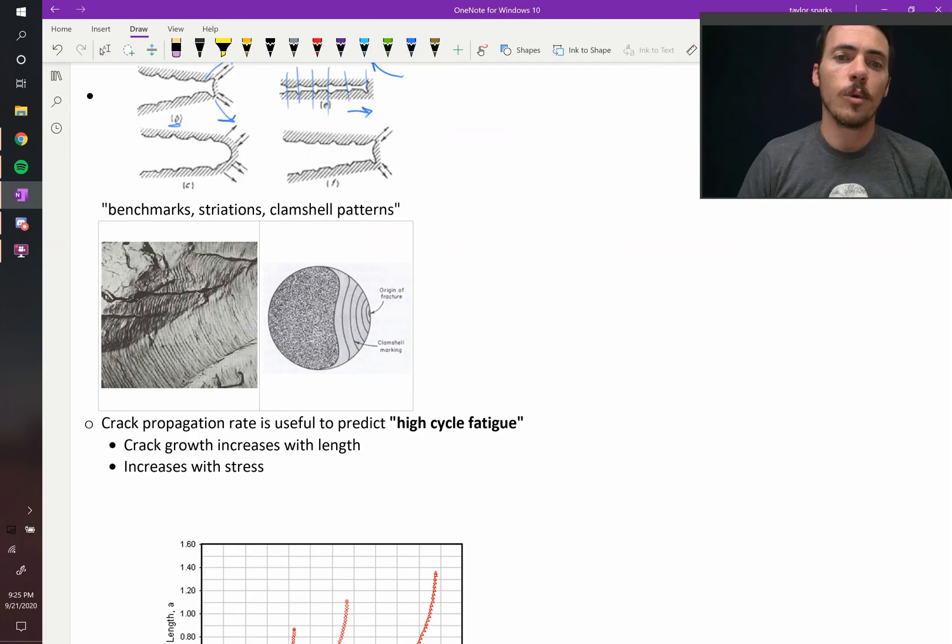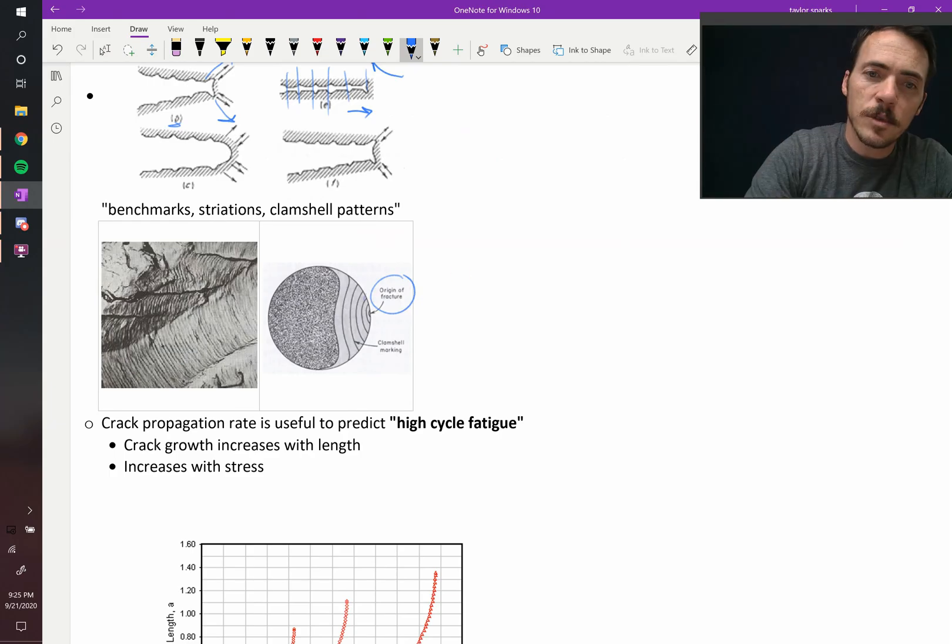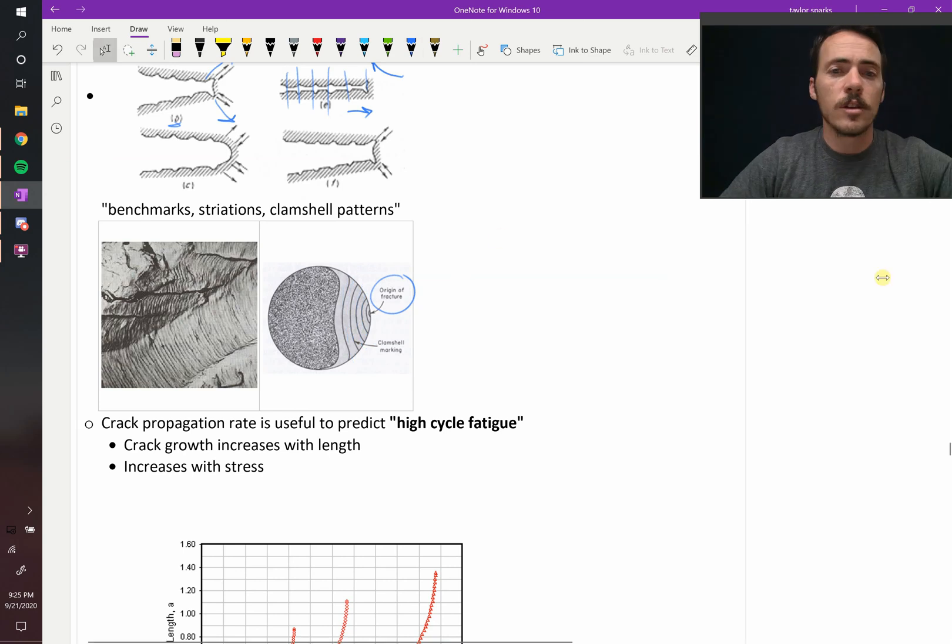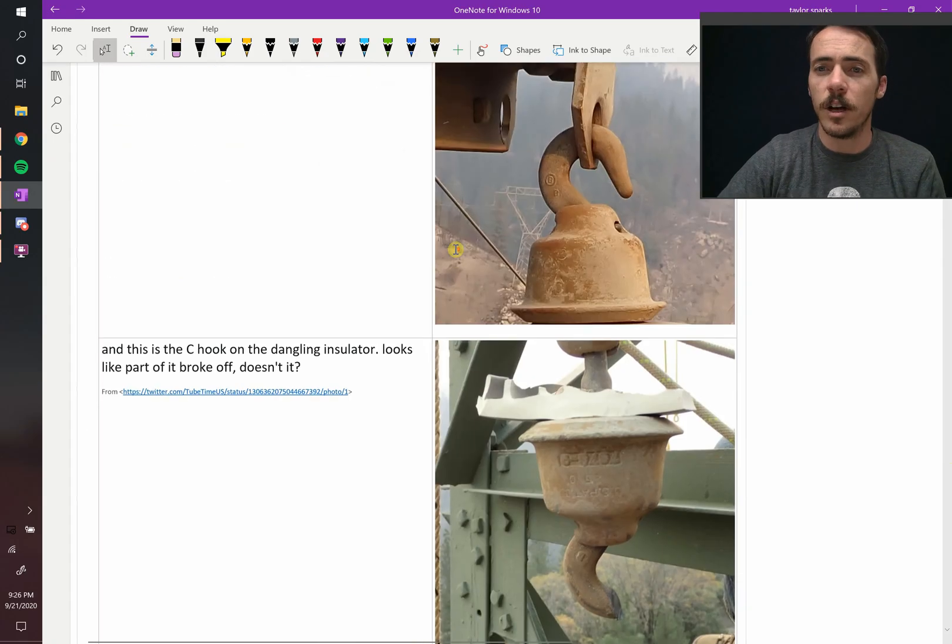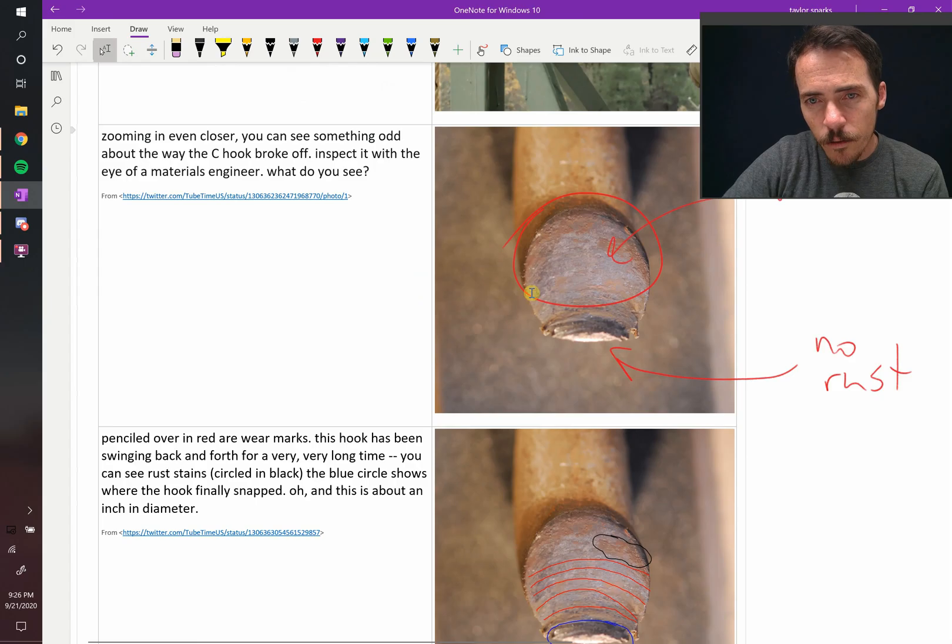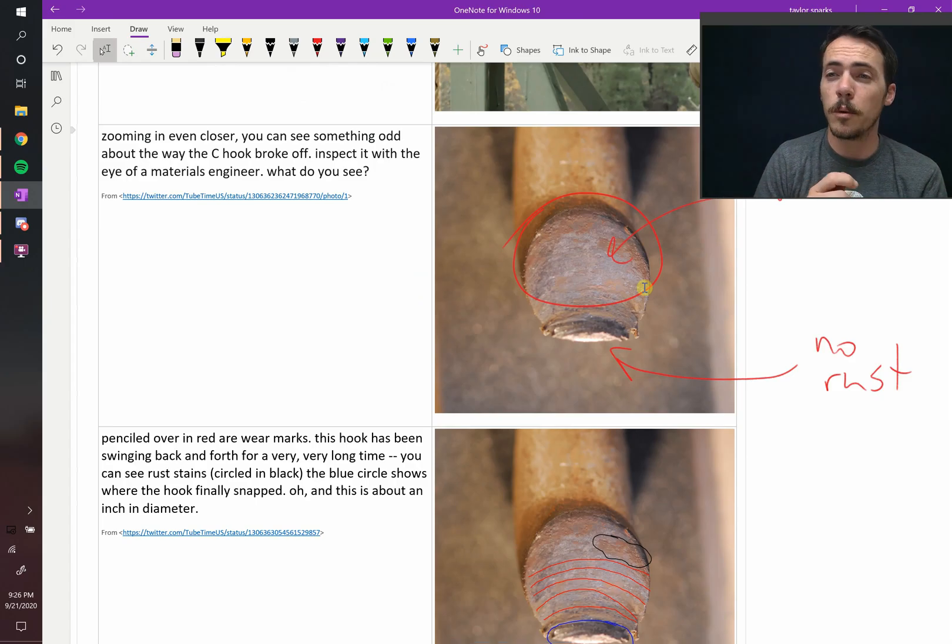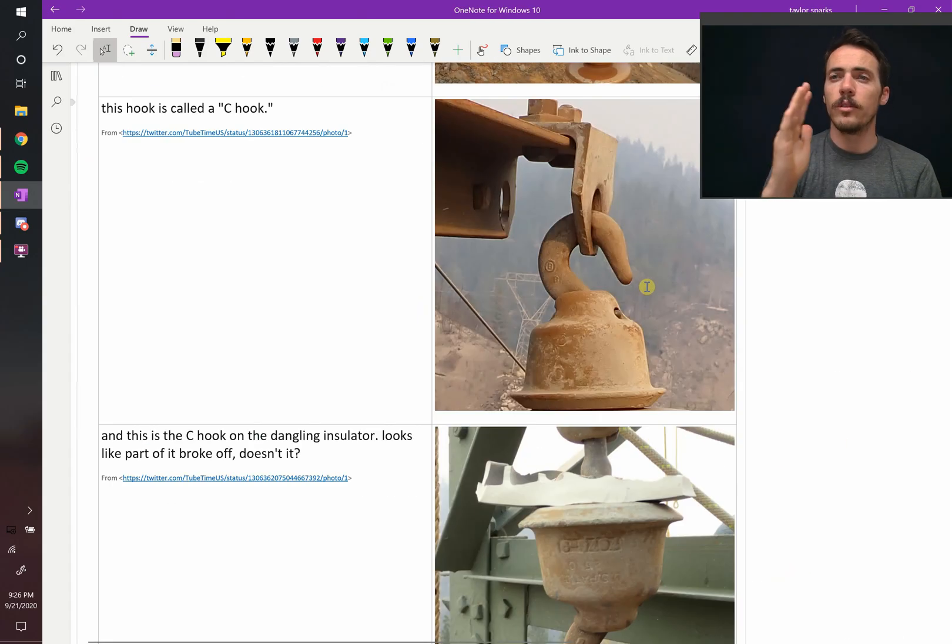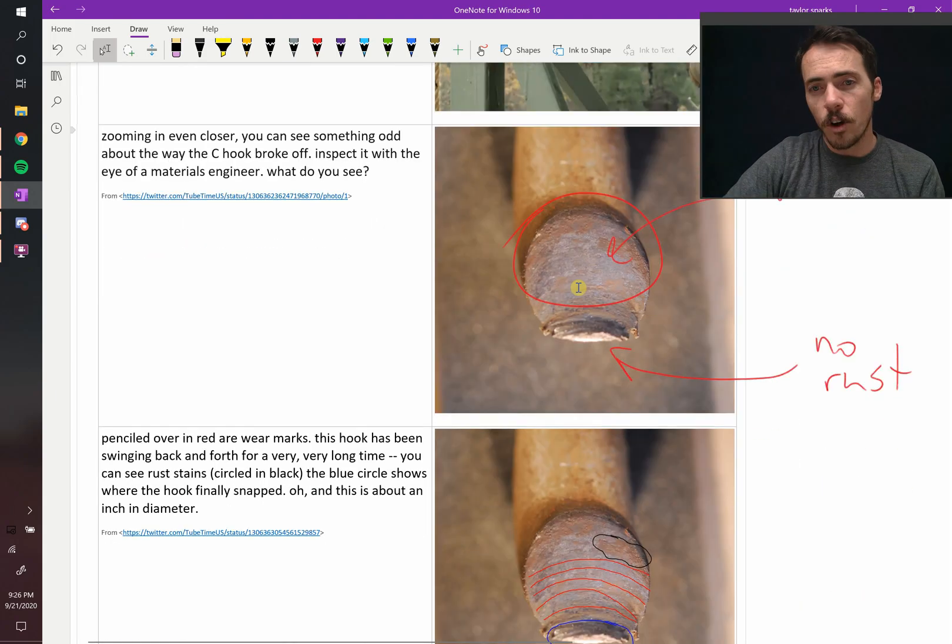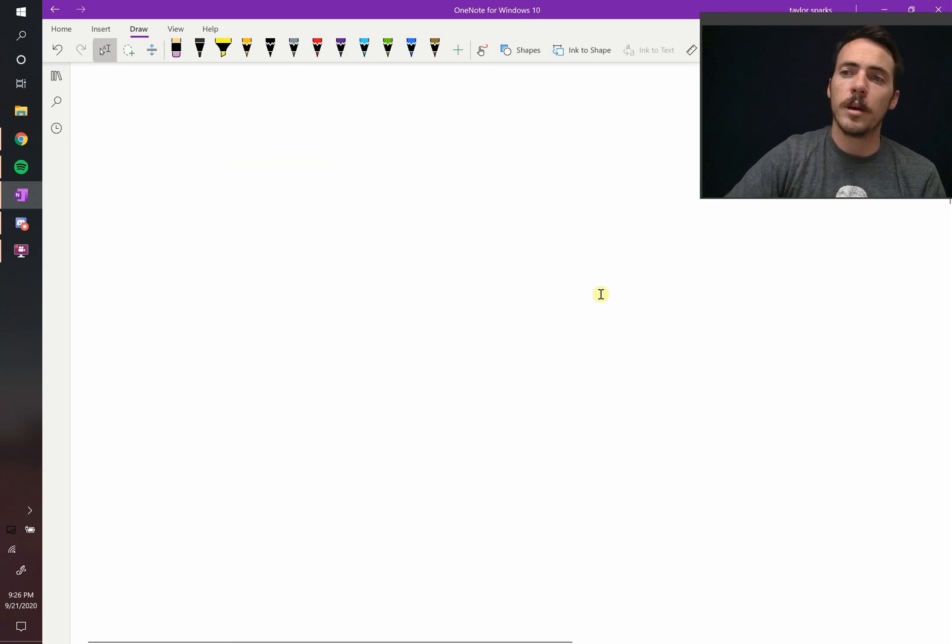And so what's really interesting is that you can see the origin of fracture, where the crack began, some sort of origin. And then you'll see these clamshell markings and you could count them up and you could count the number of cycles until failure occurred. So we saw something kind of like this in the beginning of this chapter when we talked about the C hooks. When we looked at it, you can see a series of almost like tree rings. Now, this probably wasn't a traditional fatigue. This was probably where that thing was hanging on this hook. And then as wind blows the lines a little bit, they're moving just a little bit. And so it's slowly sawing it. But nevertheless, if you were to count all those things, you could zoom in enough and actually see them. You could get an idea of how long this was going on for. So that would be an example of a type of fatigue.